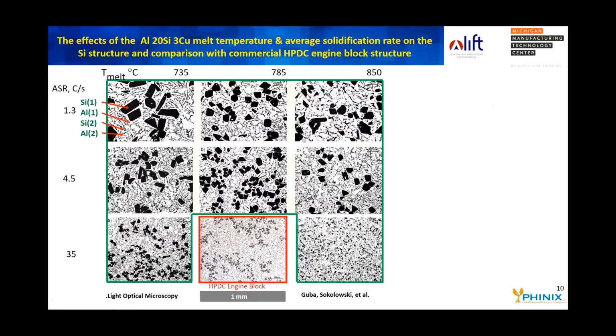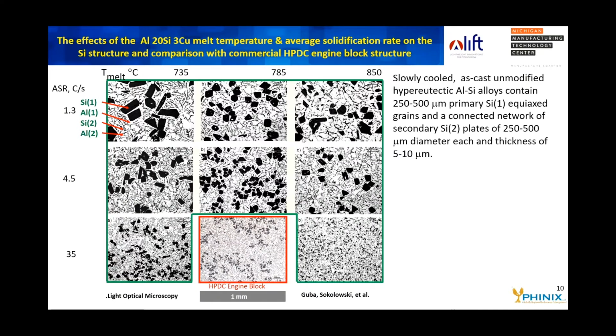There has been a lot of study on how to modify this primary silicon distribution and size, and here we show the effect of the melt holding temperature and the cooling rate, the average solidification rate, on that distribution. The slowly cooled material, top left corner, at 735 degrees and 1.3 degrees a second, contains large primary silicons and large plates of secondary silicon, and those plates are 250 to 500 microns in diameter and have a thickness of about 5 to 10 microns.